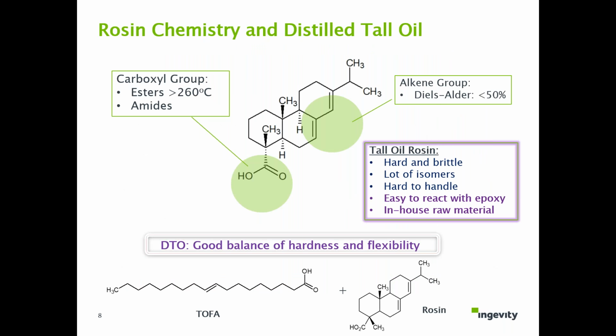When you look at this rosin chemistry, there are two sites where you can do chemical modification or reaction. On the bottom part is COOH, the carboxylic acid group. It can react with a glycol to make an ester. It can also react with an amine to make an amide, but that needs a relatively high temperature because the reactivity is not that high.